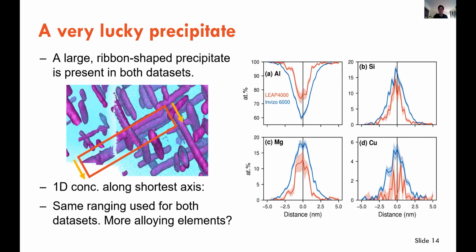I mean, these are 6000, it seems to be a little bit richer. It was exactly the same range file. Remember, the idea was to try and make these experiments as exactly the same as possible. Peak shapes are a little different in the Invizio. So the message of this slide is not the Invizio sees more alloying elements. The message of this slide is more care needs to be taken in ranging. You can't simply copy your workflows from the 4000 to the 6000. You need to work on them a little bit more.